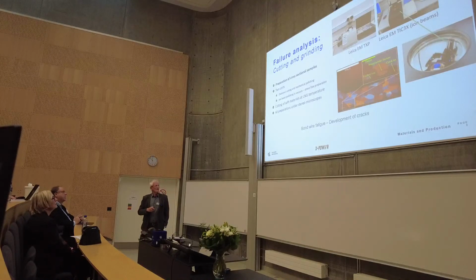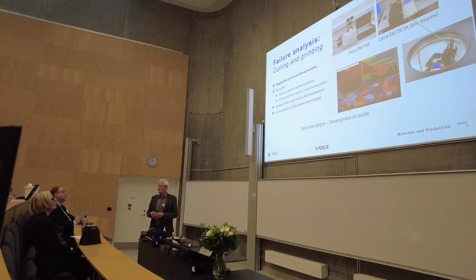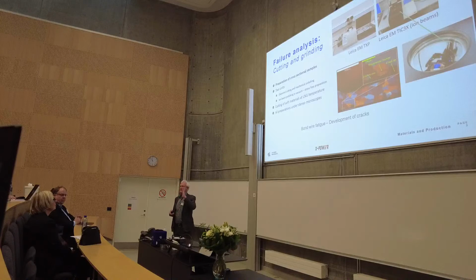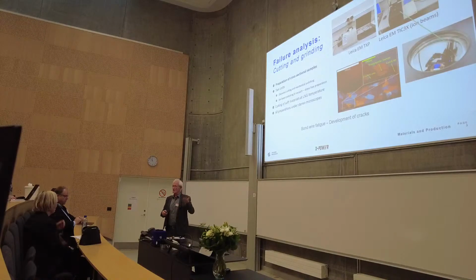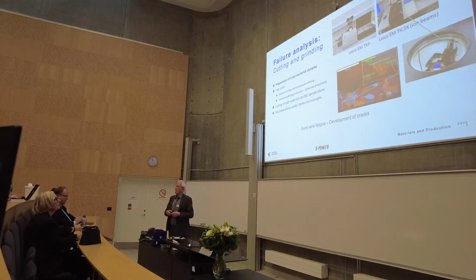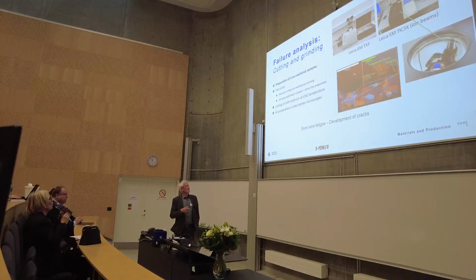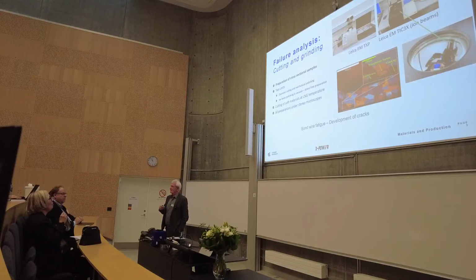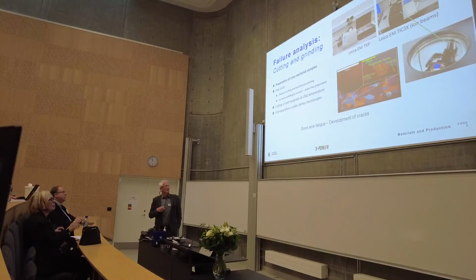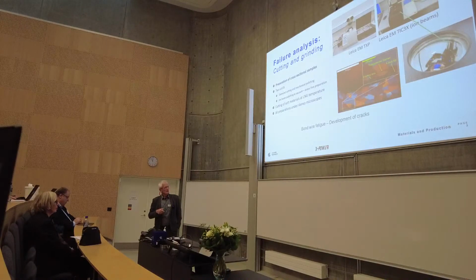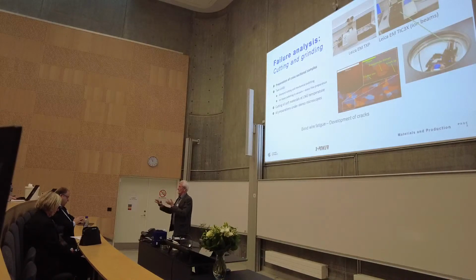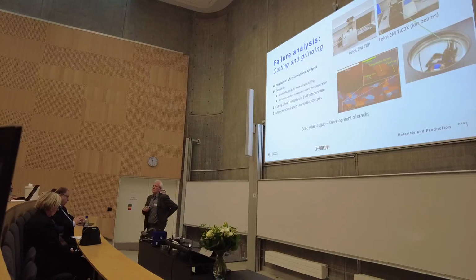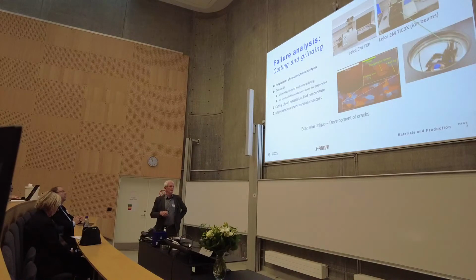It consists of 2 units from Leica. The first one, where you can cut in with a diamond saw under a microscope and try to isolate the part that you want to look at. Afterwards, in the same machine, you can polish mechanically until you have a smooth surface. But this leaves you with something that's damaged, with strains and so on. So you can move to an ion beam system, which has 3 ion beams. You can see these blue dots there that hit the sample, and so you can sputter away with ions to have a stress-free surface that you can analyze afterwards.